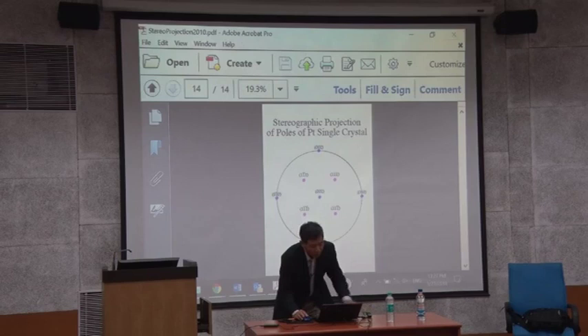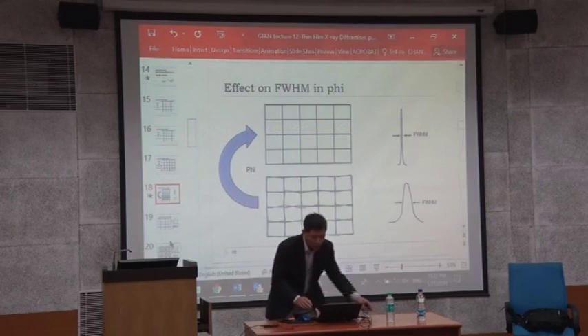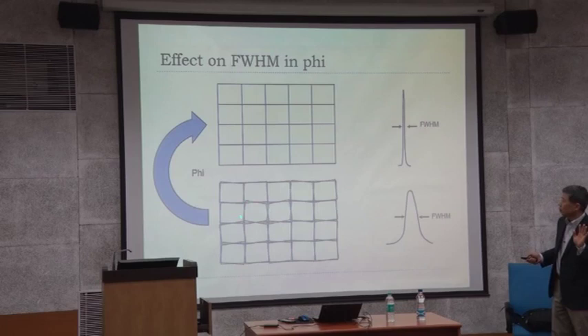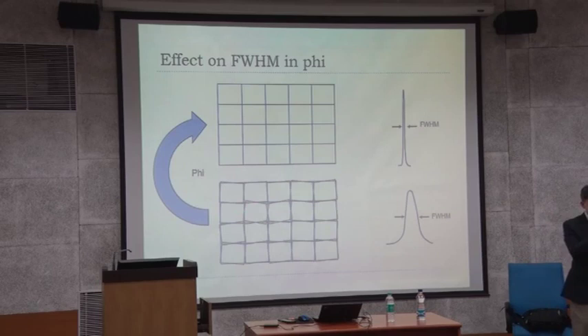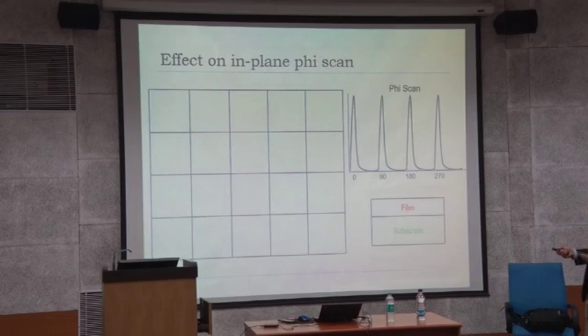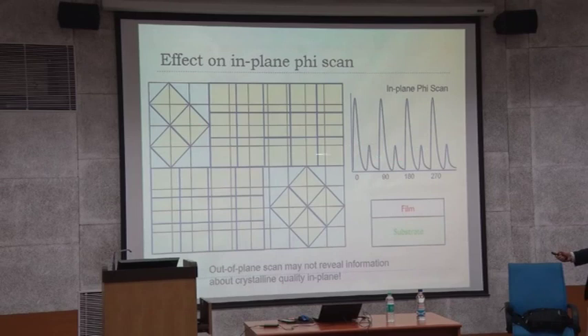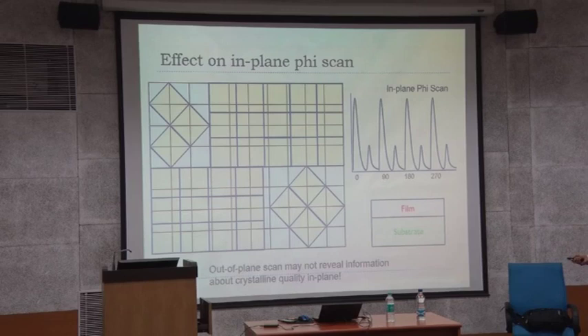This actually tells the symmetry and the mosaic spread or multi in-plane oriented domains, which is very important to determine what kind of crystalline quality you have. You use the same kind of off-axis peak, like 1-1-1. If misoriented by some amount, that gives a broadening of the peak. You have to use off-axis peaks like 1-1-1 type of reflection. The perfect one shows peaks every 90 degrees. But with a 45-degree domain, you see another peak in the middle every 45 degrees. You estimate the volume fraction of those two domains from the peak intensities.